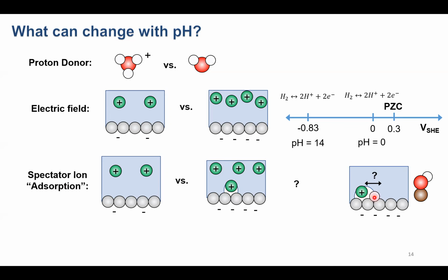And this is important because if they did that, maybe they might then interact directly with various reactive intermediates that are adsorbed on the surface. And I'll mention that the electric field across the surface could affect the adsorption energy of these reaction intermediates, could affect activation energies for various reactions occurring on our surface, as can the presence of a partially desolvated cation sitting close to these species on a surface. And so most of the work we'll talk about today is really trying to understand, is this possible? And if so, what effects does it have?